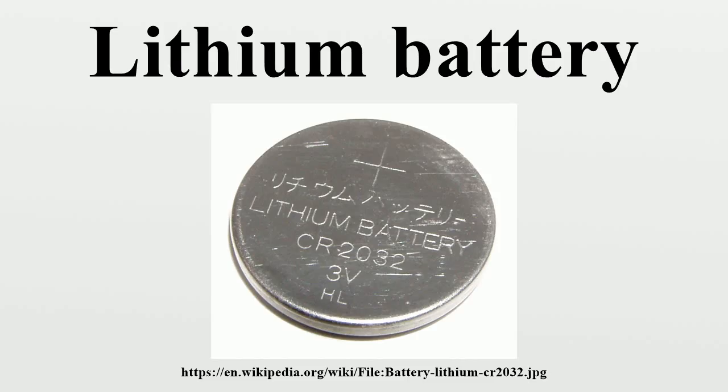Regulated quantities would not be found in typical consumer use of these cells, as lithium in used but non-working button cells is still likely to be in the cathode cup. It is possible to extract commercially useful quantities of the metal from such cells as well as the manganese dioxide and specialist plastics. From experiment, the usual failure mode is that they will read 3.2 V or above but be unable to generate useful current. Some also alloy the lithium with magnesium to cut costs, and these are particularly prone to the mentioned failure mode.